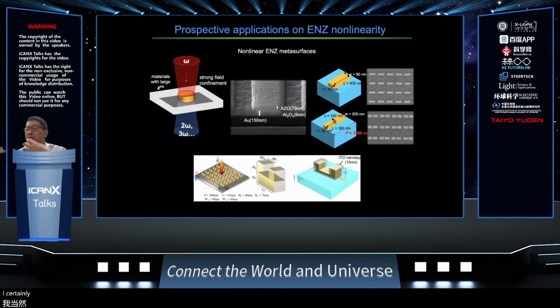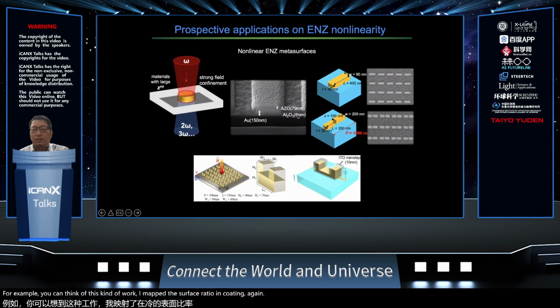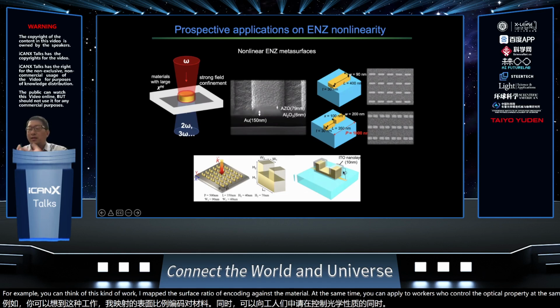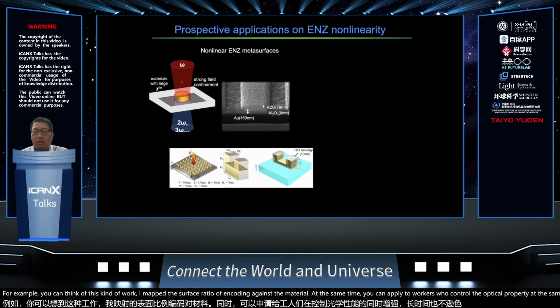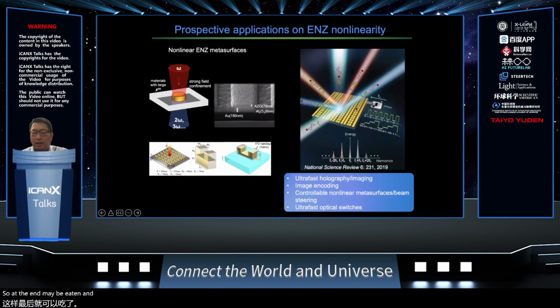Certainly, we want to integrate this nonlinear material into nanostructures. So, for example, we can think of this kind of metasurface structure. We can coat an ENZ material, and at the same time, you can apply a voltage to control the optical property, while enhancing the nonlinearity as well. So at the end, maybe you can electrically and optically tune this kind of light generation so that you can use it for ultra-fast holographic image encoding, nonlinear metasurfaces, or even an ultra-fast optical switch.